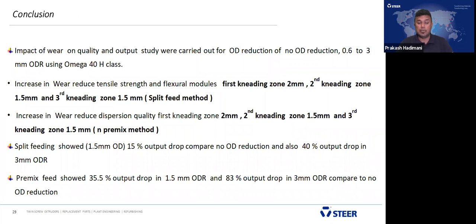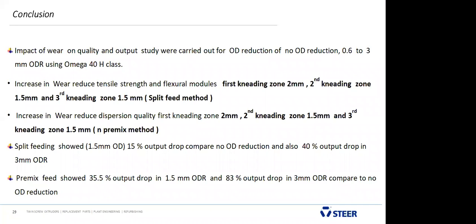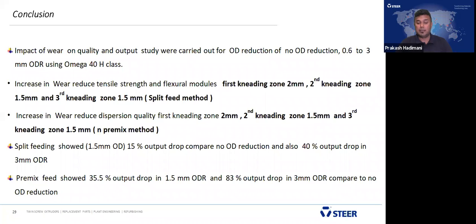Now, finally, we conclude the impact of wear on quality and output. Studies were carried out for OD reduction and also no OD reduction, starting from 0.6 millimeter, both sides. If you calculate 0.3 per side, up to 2 to 3 millimeter OD reduction. We also studied different zones and the 100% premix, with OD reduction from intake to the end, using Omega-40 H class. Increasing wear reduces tensile strength and flexural modulus. In the split feed method, the first kneading zone was 2 millimeter, the second zone 1.5 millimeter, and the third kneading zone 1.5 millimeter.